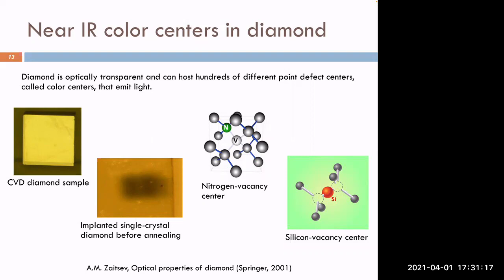With that, then you can incorporate these impurities in the growth process by, for example, injecting some gases containing nitrogen or silicon. Or that's what we do more. You take an accelerator and you implant these ions into the diamond crystal. So in this picture, you see a darker region, which corresponds to the region in which we implanted silicon ions. So the implantation process is damaging the diamond lattice, and that is why the transparency goes a little bit away, and you see this darker region.